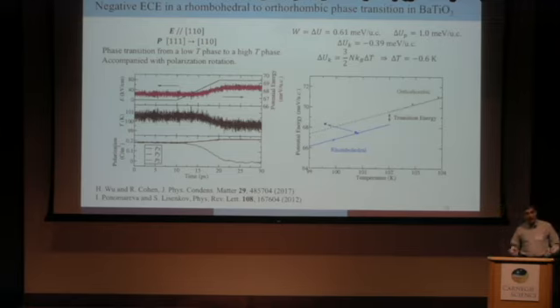You may have expected that as you apply an electric field, you orient the dipoles, making the potential energy go down. But in this case, the electric field is applied along the 110 direction. You see up here? And if you start in the rhombohedral phase, this will favor polarization along X and Y, and that will send a signal to the material to scramble its Z polarization. And that's what happens. You watch the polarization as a function of time. X, Y, and Z are all finite, but then upon experiencing this electric field along the 110 direction, it becomes orthorhombic.